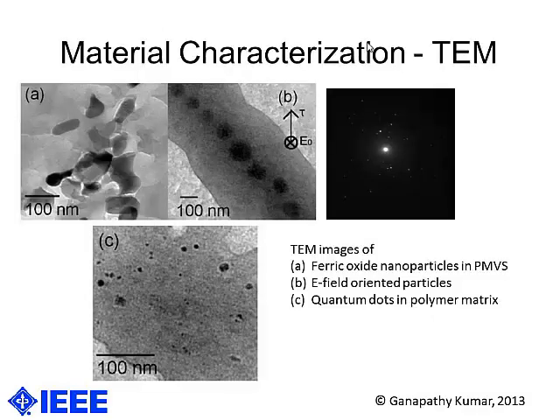Now for the material characterization, we characterize this particular material using small angle X-ray scattering and transmission electron microscopy. Figure A is showing you how the sample looks when there's absolutely no orientation. Figure B is where we're looking at a sample where the nanoparticles have been oriented. There's an electron diffraction pattern showing that we're not looking at some striations or some bad formations in the polymer, but rather we're looking at the exact material.